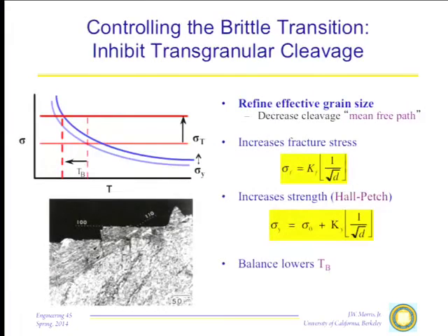If you beat intergranular fracture, then what you're left with is the inherent fracture, which is transgranular. You get nice flat faces that look something like this. This is in a steel. Even the microstructure of martensitic steel is such that even though it looks like we have all kinds of grains here, they're actually crystallographically identical. So essentially this is a single crystal. And here you see the cleavage cracks going across the grains. Iron BCC metals cleave on 100 planes. And here you see the flat 100 planes.